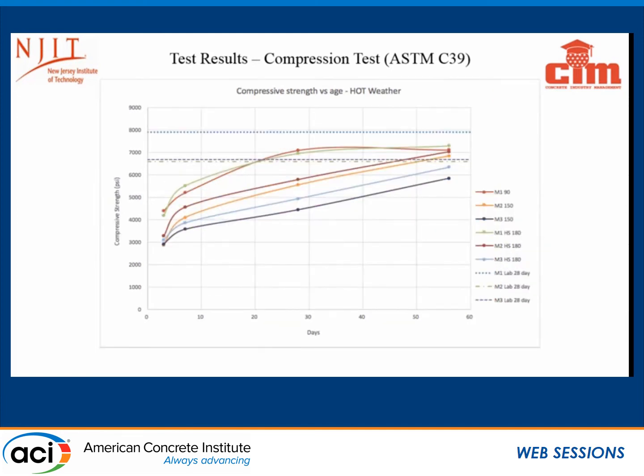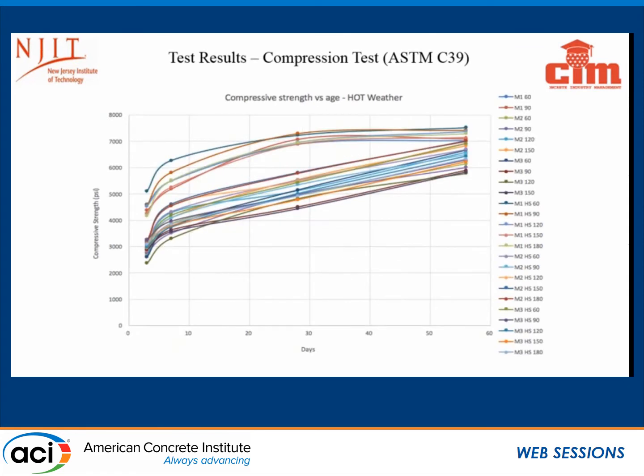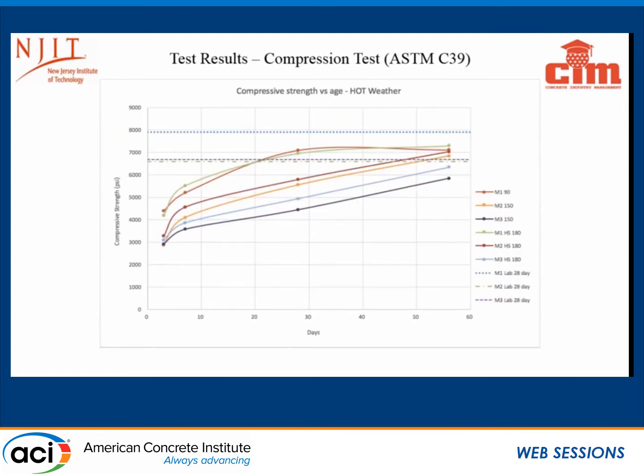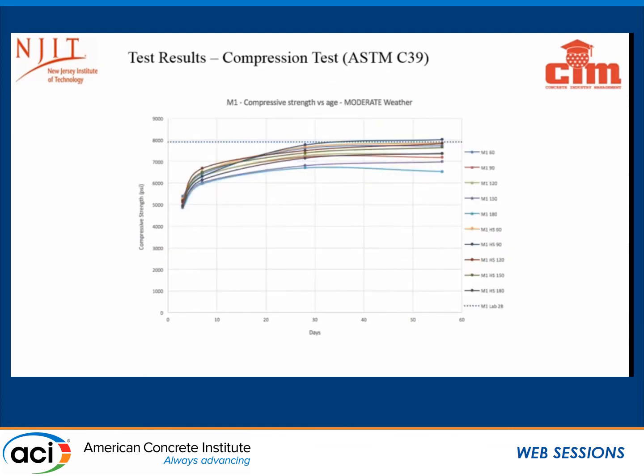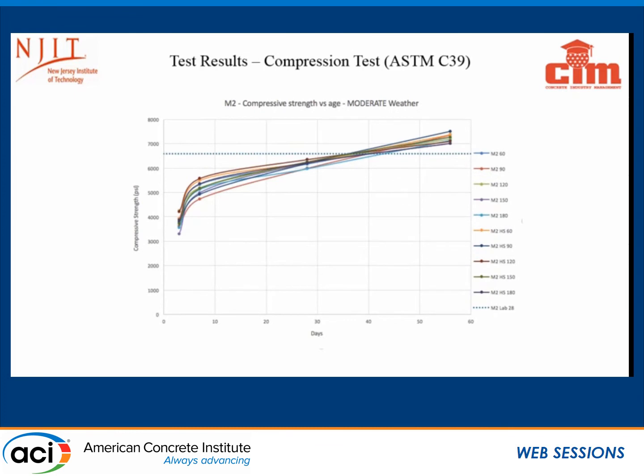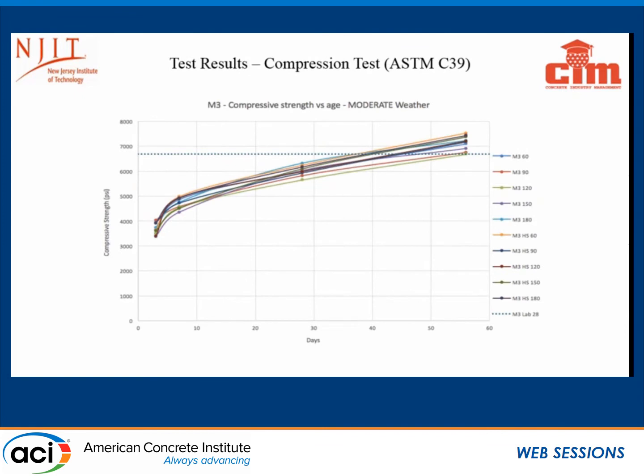Here we have it broken down a little bit. This one is pretty much all of the mixes. This is hot weather mixes by itself. As you can see, the graph is not all congested, and we're hitting our targets. This one, mix one, which, if you recall, was just 100% straight Portland cement, is hitting our targets. Mix two, in moderate weather, you're still hitting your target. Mix three, in moderate weather, hitting your target.